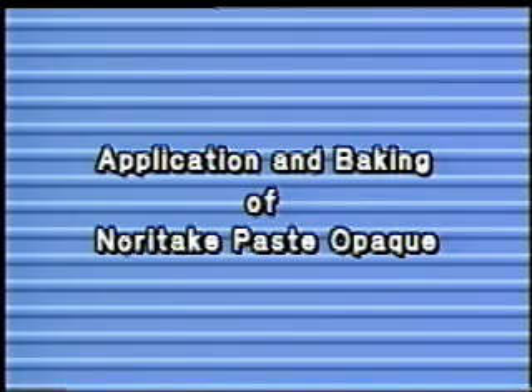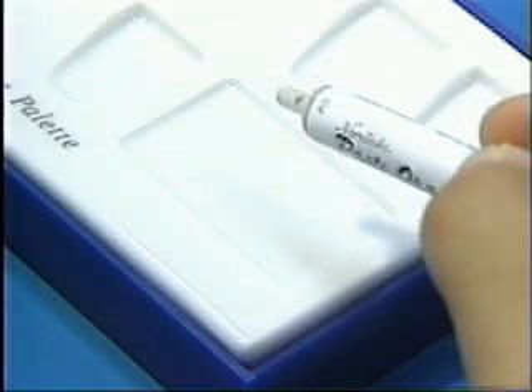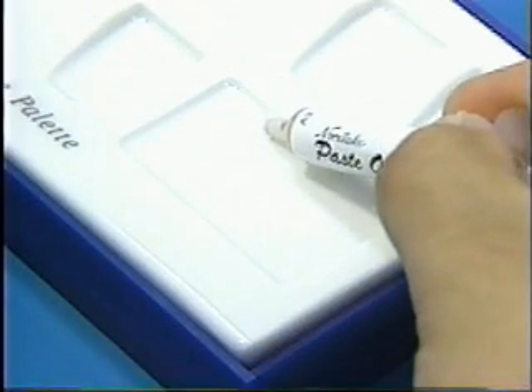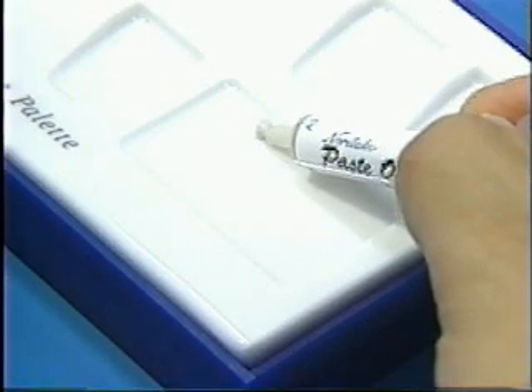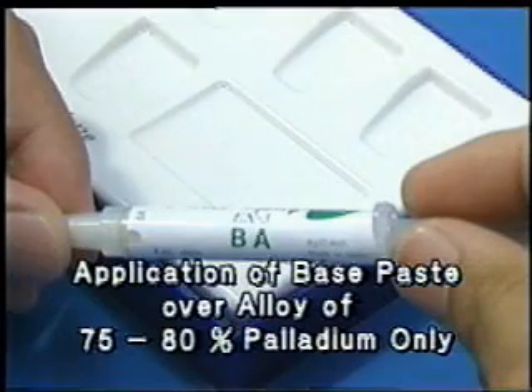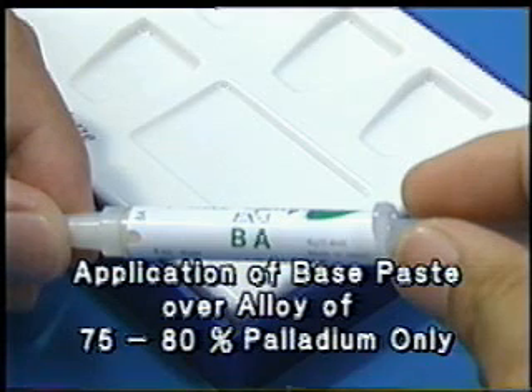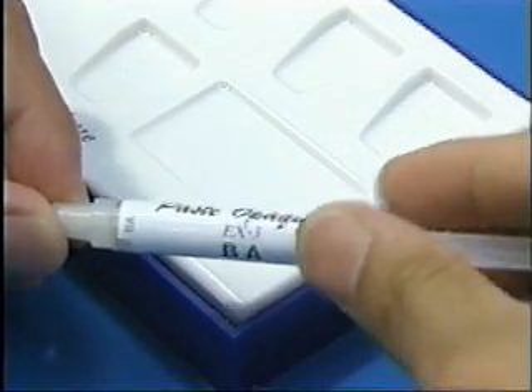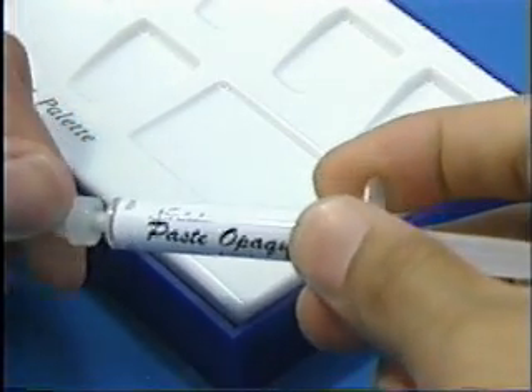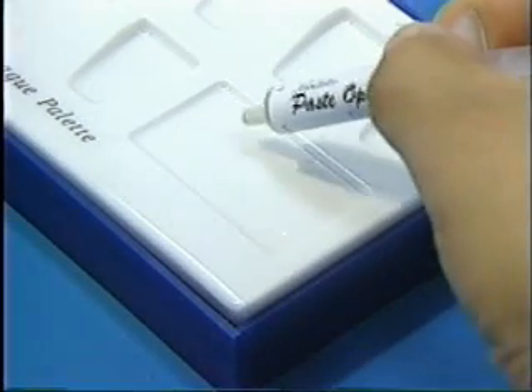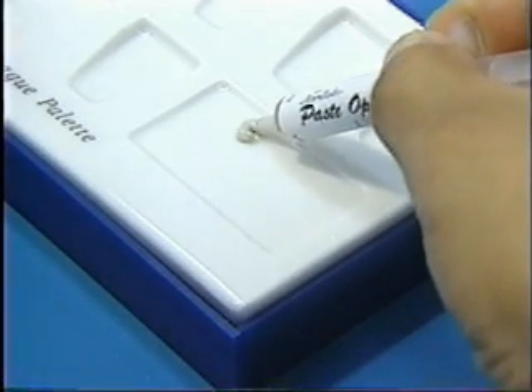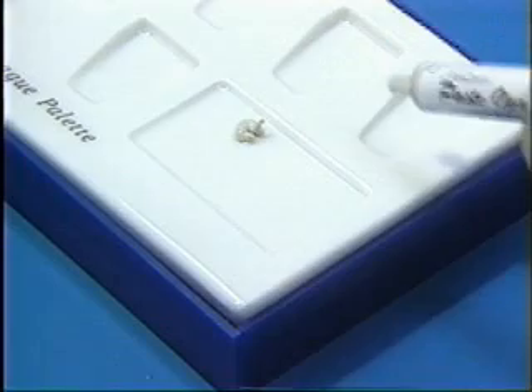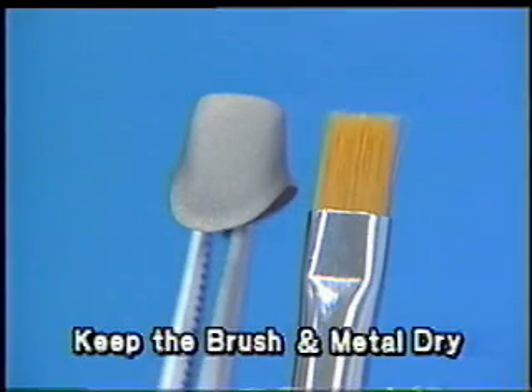Now we move on to the handling of EX-3 paste opaque. Squeeze out the paste opaque from the syringe and load it onto the palette. For a general shade, apply the paste opaque as instructed, but for application on the alloy containing 75 to 80% palladium, base paste BA is preferred. The reason is that the alloy of palladium has copper as a component, so BA is applied compatibly to prevent greenness caused by copper.